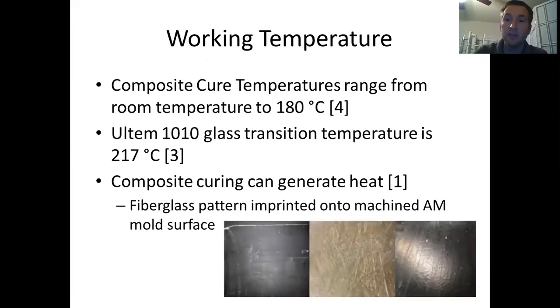So the first design aspect is the working temperature. A lot of composites are cured at a high temperature and pressure, anywhere from room temperature up to 180 degrees Celsius. And ULTEM 1010 has a glass transition temperature of 217 C. So that puts you about in the ballpark of being able to use the ULTEM as a core in a heated curing cycle of a composite. But it can also be used for non-heated curing cycles.